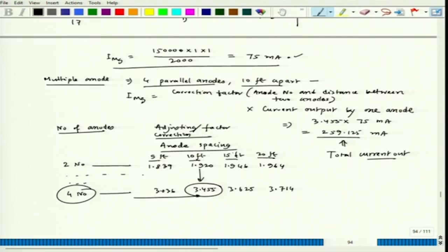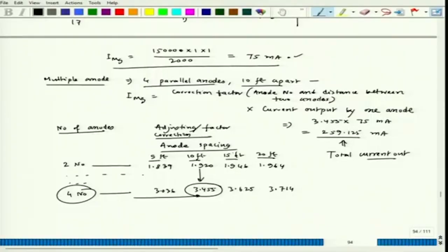The only difference is that the correction factor comes for other reasons, because when you use the basic equation V equal to IR, that R contribution would be different at different segments and junctions. For example, there could be one IR due to the backfill and the anode, then the backfill and soil, and then the soil and pipe surface. All those resistance factors would come up. So it's not exactly the current given by one anode multiplied by the number of anodes to find the total current output. There should be a correction factor because of those variations in resistance, dimensions, shapes, all those factors. We don't get into those complications. This is a simplified way of looking at it.